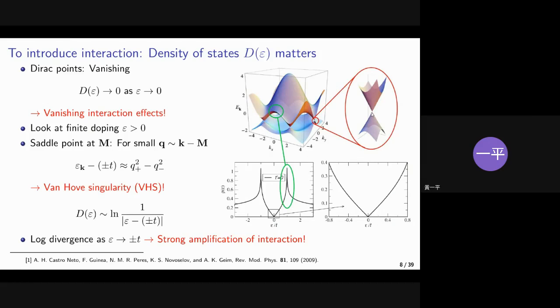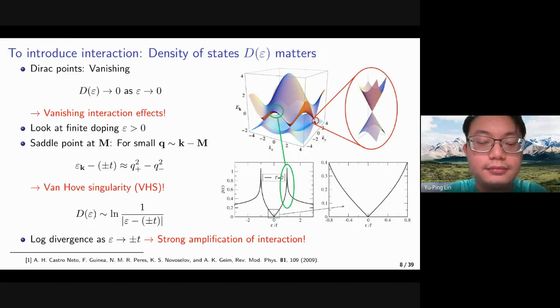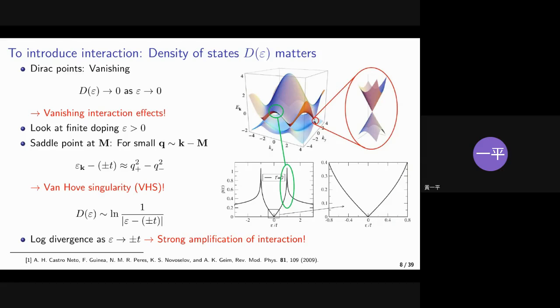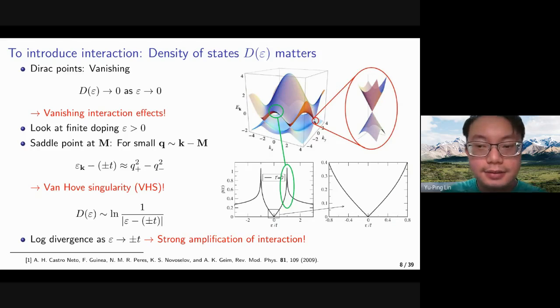I see. So the statement is that assuming the coupling is not too strong, then the perturbative argument will suggest that the vanishing density of states actually leads to weakly correlated physics. But there's a threshold: once the interaction is too strong, the suppression of the screening effect will kick in. Then the theory will become basically a strong coupling theory. So you are working in the weak coupling region, and ask if you dope your system such that the chemical potential is sitting at the saddle point of the band structure, then what's the effect of the Van Hove singularity in the weak coupling scheme? Yeah, that's true. Okay, thank you.